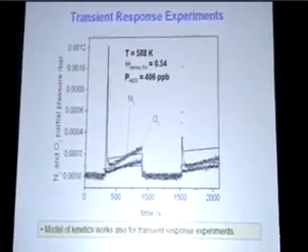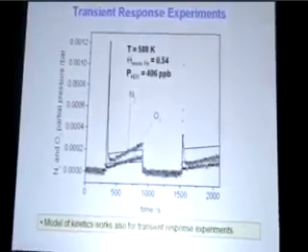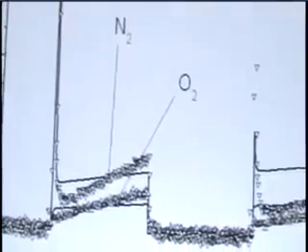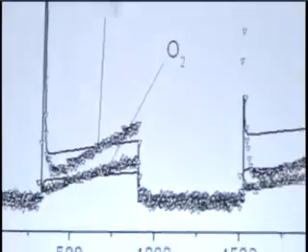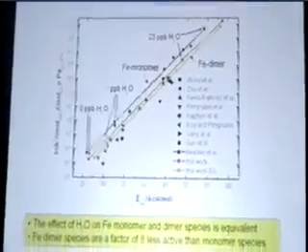And the temperature is low enough that the release of that oxygen is sluggish, and we don't see it right away because we have to have a second oxygen come in and combine with the first. But if you wait long enough, you can begin to see the first traces of the steady state activity. And so you see the data points and the solid lines here represent our theoretical calculations with no adjustment in any of the parameters.